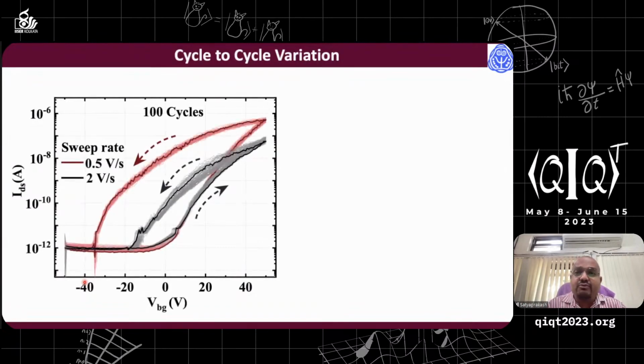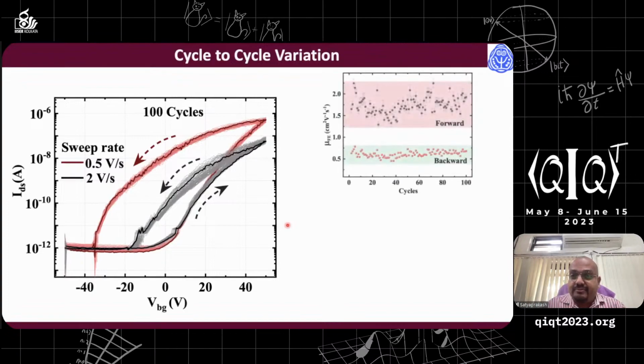Now coming to the cyclic variation, we have done say 100 cycle variation by just changing the sweep rate, you can see here there is a narrow change. You see how close or how narrow these changes are. They're quite repeatable and quite consistent. That gives an indication that these materials can be used for a long-term memory application.